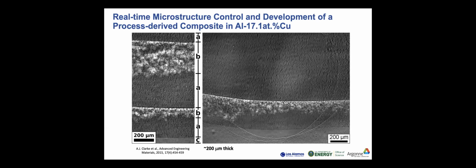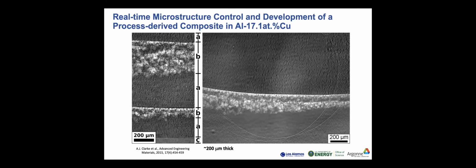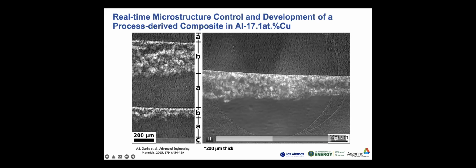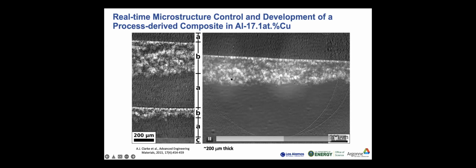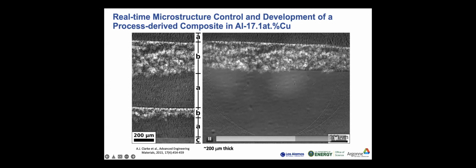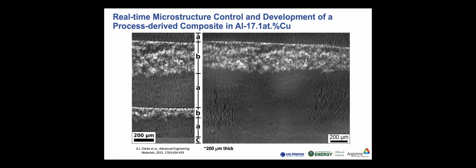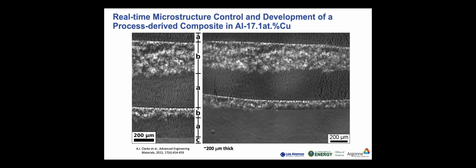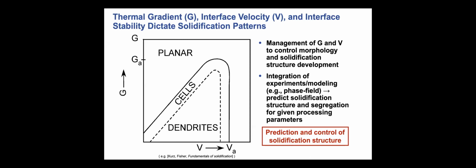So in the previous slide, I showed you an example of that aluminum rich part of the eutectic breaking up into these matchstick fragments. Here we actually see coarsening of these particles, and they're sort of spheres and they're floating at the solid liquid interface. As we melt the interface back, we then progress the solid liquid interface forward, lock in that layered structure, and wash, rinse, repeat. We create another layer in the structure. So this just again highlights that with the benefit of being able to see the way microstructure develops, we can really have microstructural control. And again, this is just a fun example of this process-derived composite highlighting that.